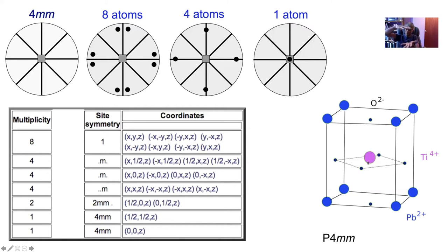And that's why when we deform the material, the charges are not displaced equally, and therefore we end up with a dipole. So that is the correct solution of the crystal structure of lead titanate. And the titanium atoms are located a little bit above the body center, and the lead atoms are located a little bit above the corner. So these 4 atoms are not actually in the unit cell, and these atoms at the corners are actually on the edge of the unit cell, and therefore they are shared between 4 cells. So you have 1, 2, 3, 4 times a quarter gives you just 1 atom.